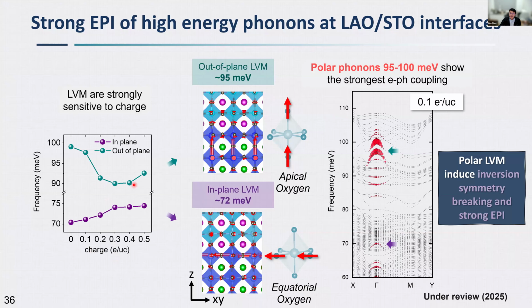And the final part is that we calculate to verify that these 2 modes actually have very strong electron-phonon coupling. We calculate the phonon line width, and you can see that this out-of-plane vibrational mode and the in-plane vibrational mode all have larger phonon line width, or stronger electron-phonon coupling. And the strongest one is coming from this out-of-plane vibration that corresponds to the apical oxygen.